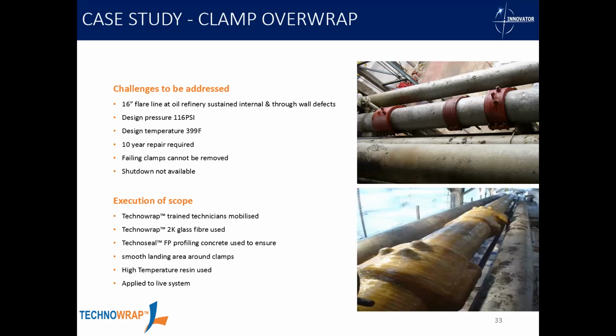And this one was a repair we did in South Africa. And what's slightly different about this one was they had to apply some clamps first to stem that leak. So the clamping was carried out by some technicians on the site already, not our technicians. They clamped it up, but then they wanted to get design life. They wanted a fully engineered solution that would last them 10 years.